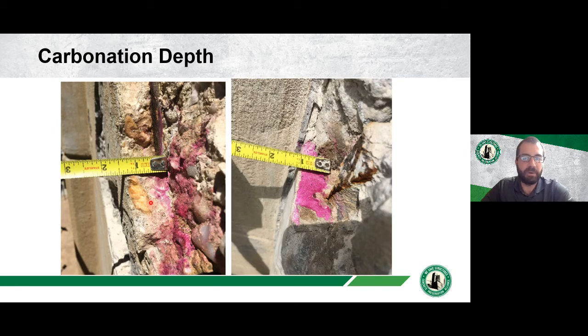So we broke a fresh area over here. There was some corrosion here, but there was also an area nearby where the pH was kind of high. So you see that the carbonation is not uniform on this structure. It depends on the concrete quality at the time of the pour, the aggregate distribution, and things like that. So on this structure, due to the age of the concrete, the carbonation was not very uniform, and so different areas were corroding at different rates.